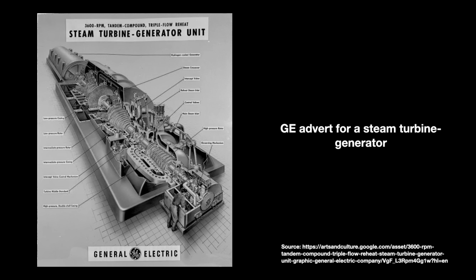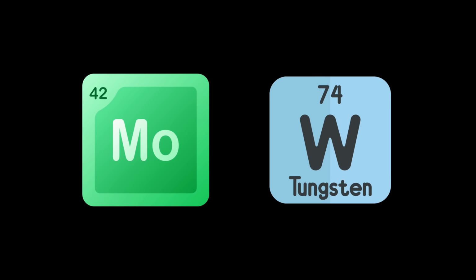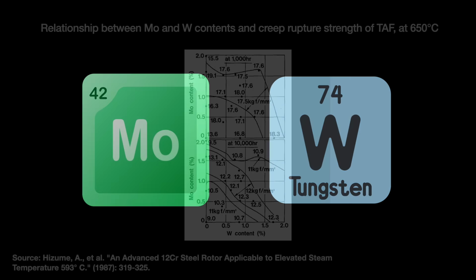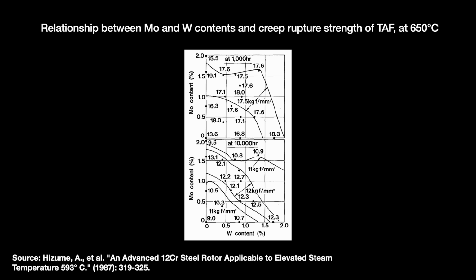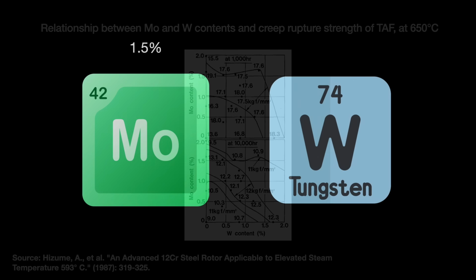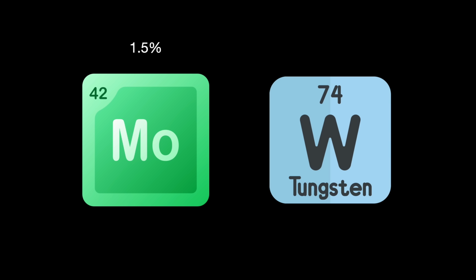To create TAF, the Japanese simply had to do one thing: tune the amount of molybdenum in relation to how much tungsten was in the steel. This was done thanks to experiments on H46 done by Professor Fujita in the 1970s. Fujita discovered that raising molybdenum content from 1% to 1.5% helped hold together the steel's internal structure and keep it from creeping. Too much molybdenum, however, would cause the steel to create delta ferrite structures that undermine that long-term creep strength. So 1.5% precisely. No more, no less.